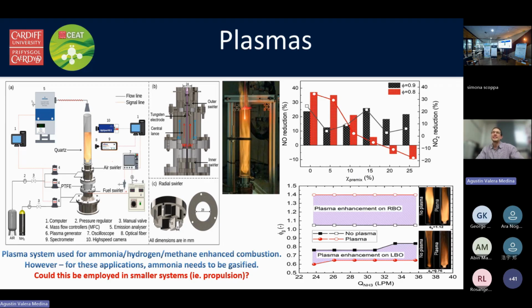So what we started doing at the time was looking into the production of some plasma systems, a gliding arc, a simple type of system, similar to those that you can see in Frankenstein movies. And then from that, give it a go, hope for the best, and test some of our burners using this technique. And surprisingly, what we found out was, first, the stability improved. Second, nitrogen oxides as well were improved, even in the worst case scenarios where you have very high NOx, like is the case when you have an excess of oxygen in the flame. And with that, we saw this big potential of using plasma systems in our units.